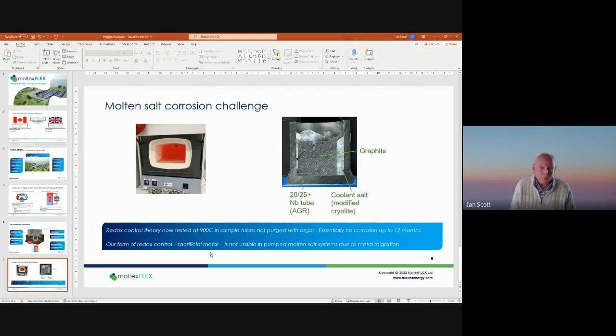That is not, in my view, the way to go forward. The way to go forward is to arrange it so that your molten salt is actually not corrosive. We've put quite a lot of work into this because the community out there is very skeptical about corrosion in molten salts, so data is important. We've now run samples using our molten salt stabilization technology at 900 degrees centigrade for up to a year with essentially no detectable corrosion at all.